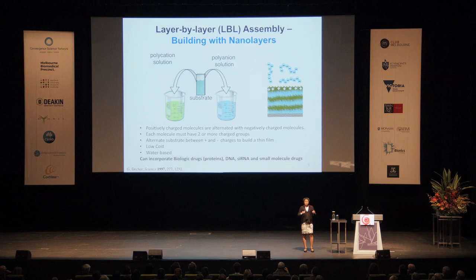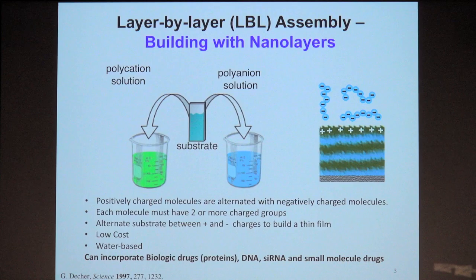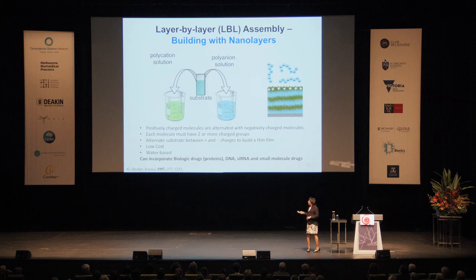And if that water solution contains a positively charged molecule, a molecule that has multiple positive charges, then that will actually adsorb onto your substrate because it's attracted to the negative charge. You'll continue to see adsorption take place until ultimately there's enough down on that surface that you have reversed that negative charge and now have a positive charge. At that point, on the substrate, you have positive charge. And in solution, you still have positively charged molecules, but now they're repelled from the surface because now you have like charges that repel. So you have a self-limiting adsorption step.